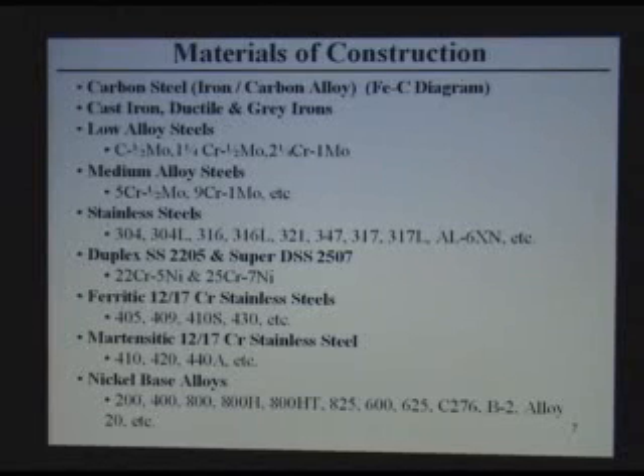Ferritic steels are predominantly 12% chromium or 17% chromium. They are used for trays and maybe some parts of the rotating equipment. There are also martensitic chrome steels, which have a higher carbon content. They are not easy to weld, but they are good for high strength properties. We also use nickel alloys for high temperature applications and very corrosive applications.